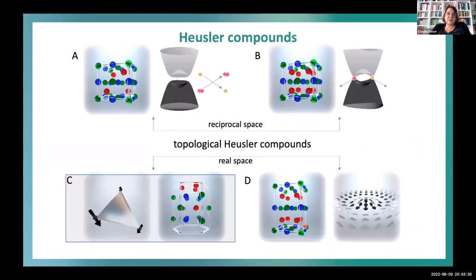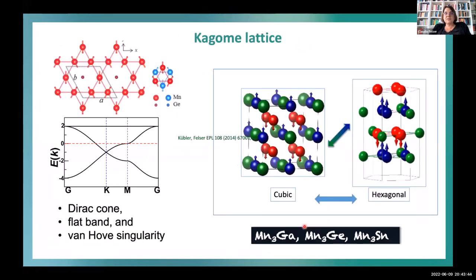I simply want to continue to manganese tin, which is also, by the way, Ajaya's experimental work. The manganese tin is a very interesting material because it's hexagonal. What we found in theory, first with Dilin Zhang and then later in this nice work which I did with Jürgen, is that it has this very nice Kagome lattice. Because of this Kagome lattice and the compound being antiferromagnetic, it has frustration. This is what people were always interested in, triangular physics.